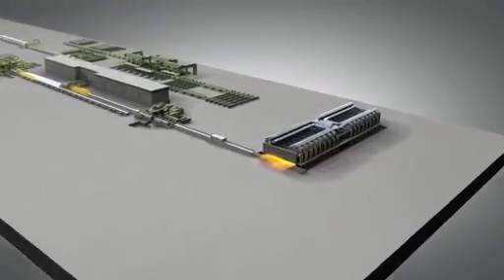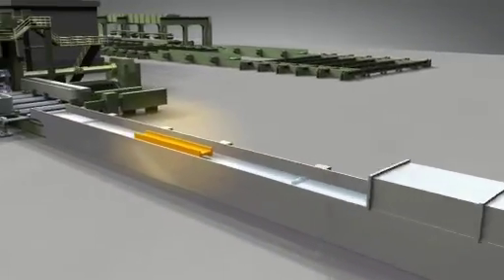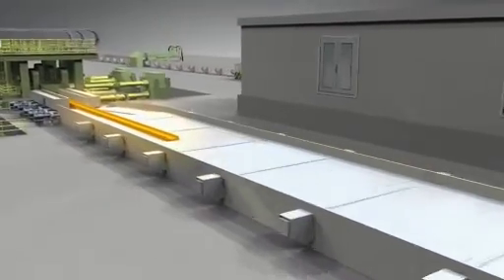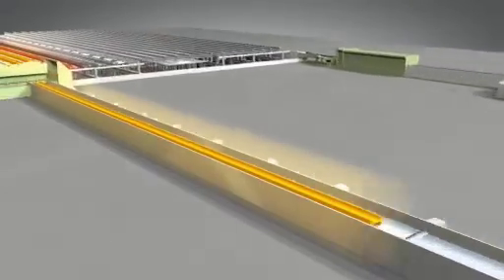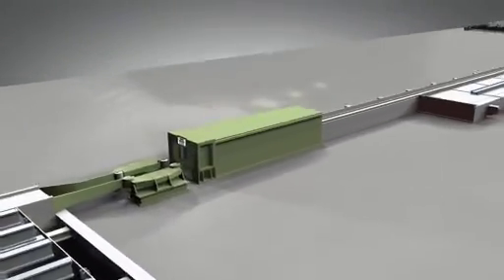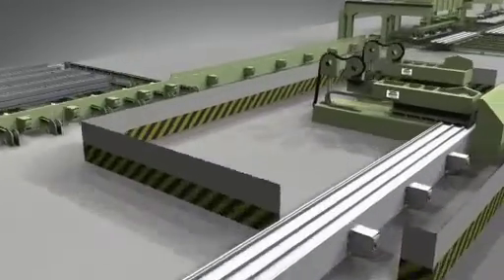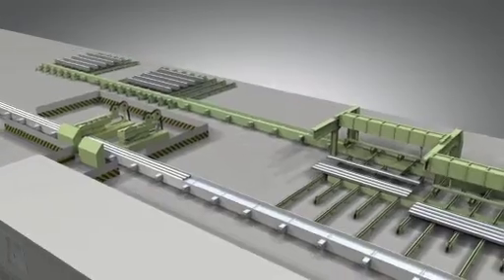The integrated line concept reflects the latest SMS Meer section rolling technology, starting from the reheating furnace, through the high-pressure water descaler, the reversing roughing stand, a cropping saw, cross-transfer unit to the second rolling line, the CCS tandem reversing group, the cooling bed saw for crops and samples, the combined walking beam chain type cooling bed, the hydraulic actuated CRS9 roller straightener with straightener rollers supported on both sides, the layer collecting bed, the cold sawing line with a pre-cutting saw and the tandem saws, and the automatic labelling and stacking facilities with the downline tying and loading equipment.